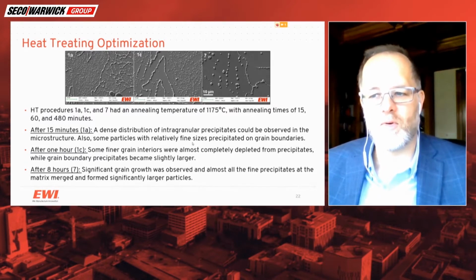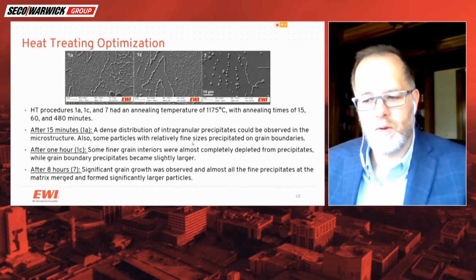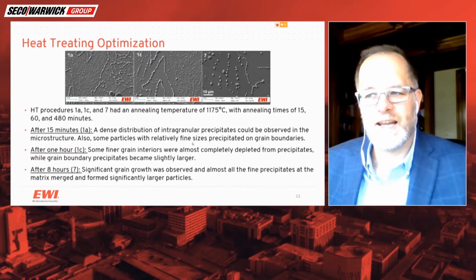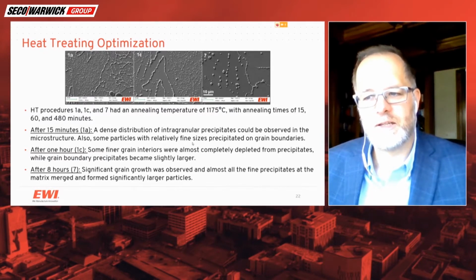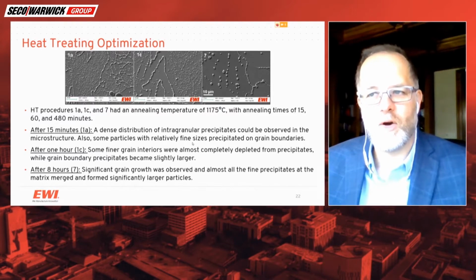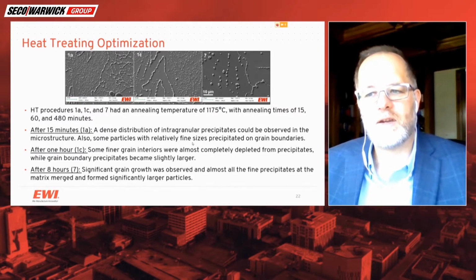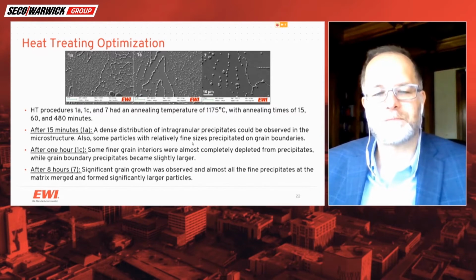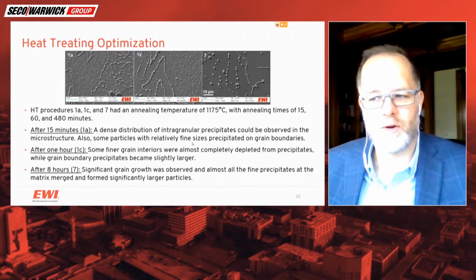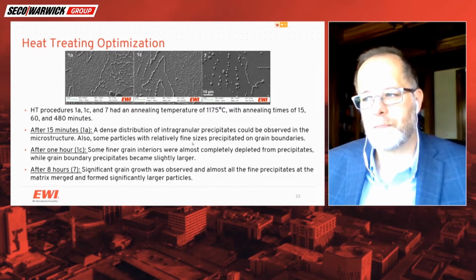And so it's very important to look at your build, look at the parameters, and it does vary a little bit between the technologies. So it's not just you can take a powder and know that you have the right heat treat. You need to take as-built parts and heat treat those and determine what's the optimum one for your process, your material.